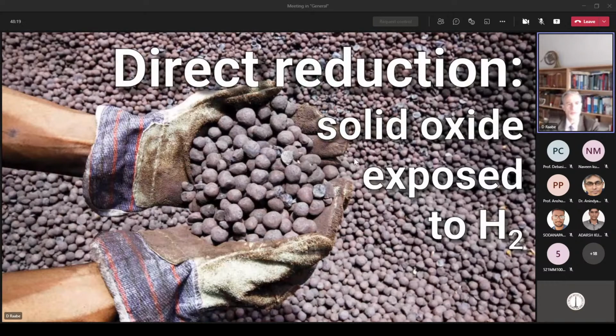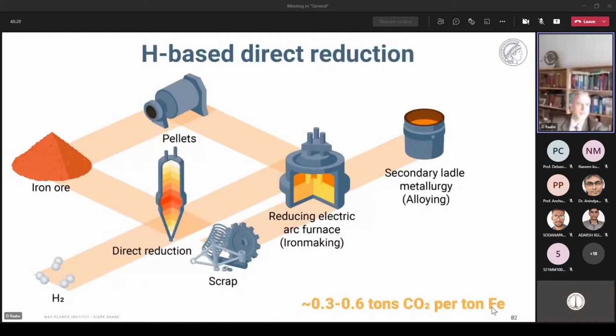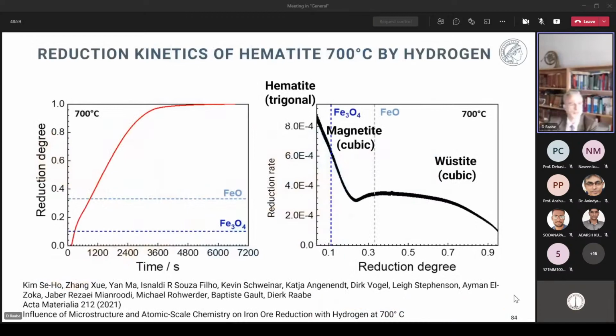And here we do these experiments with solid agglomerated fine ores that are agglomerated into the pellet form, about 1 centimeter size. And this is the industrial scenario that you know very well, and many such plants already stand in India, for instance, where you use direct reduction, charge it with pellets, which in itself is a relatively costly and expensive process. And then you bring the iron sponge that you produce into the electric arc furnace, for instance, and do the ladle metallurgy and cast it and so on. And that has already a relatively low footprint if you would operate it with hydrogen. Currently, it's of course typically done with natural gas, for instance.